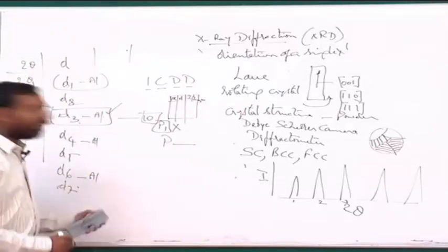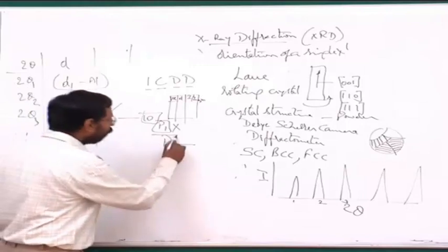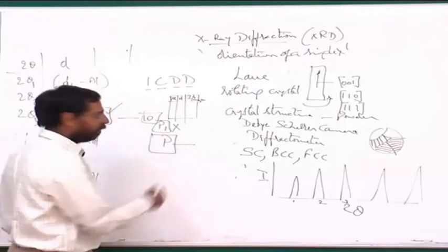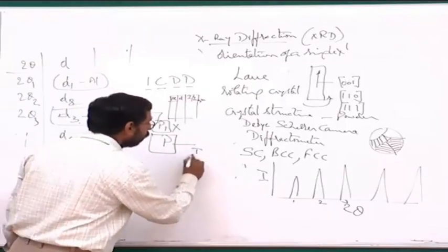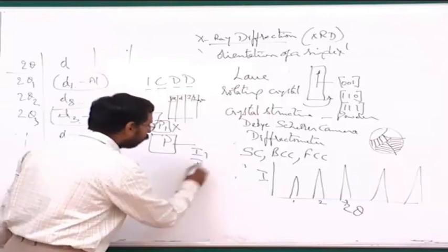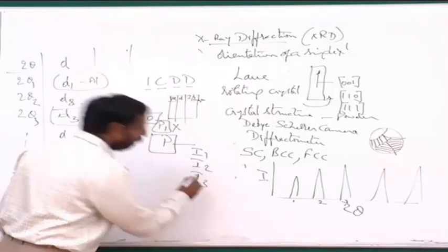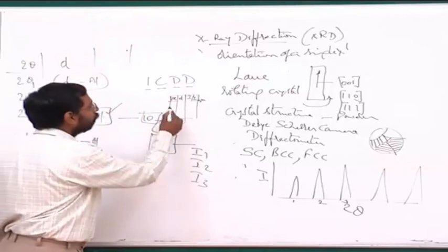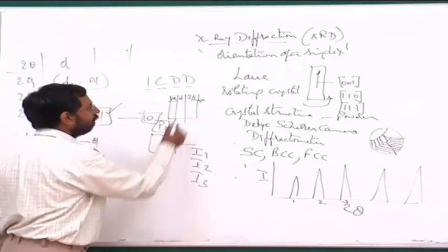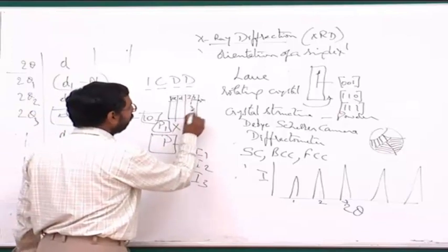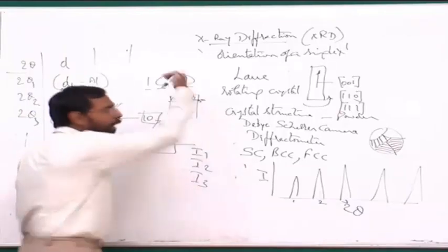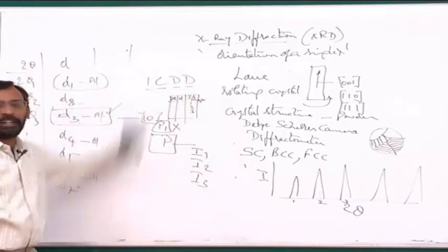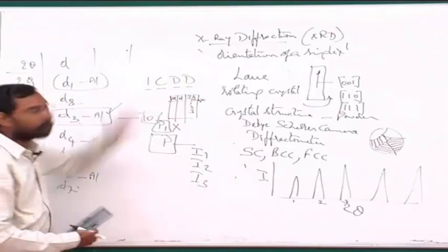Once I say yes, then I look for the other 2 intense peaks. If this is the most intense peak, which I will call I1, then look for I2 and I3, the second most and the third most intense. Identify which Ds those are; they may not be in the same order, decreasing or increasing order of D, but in some other order.